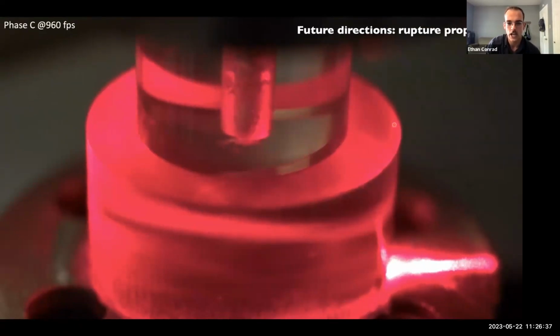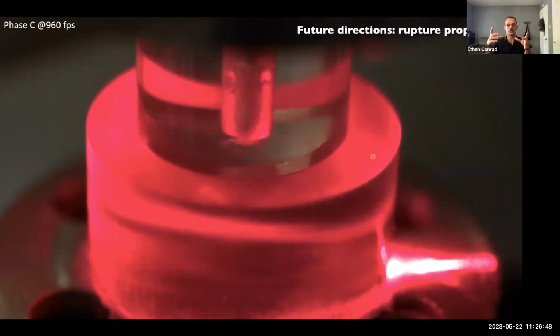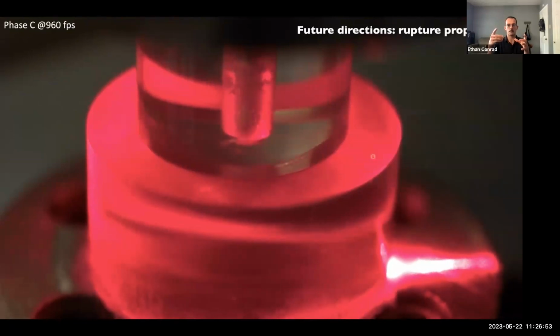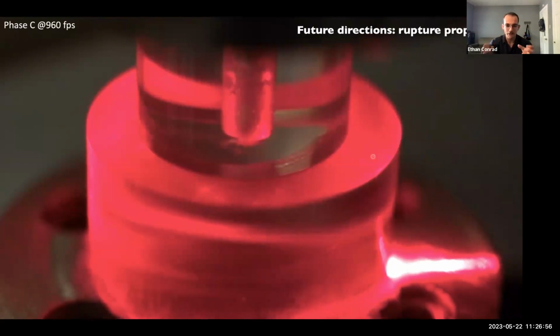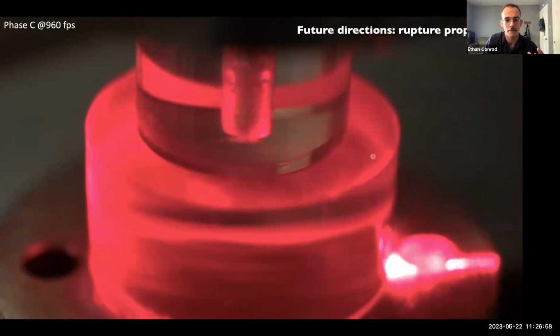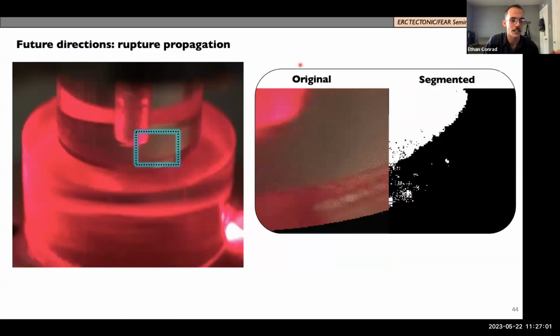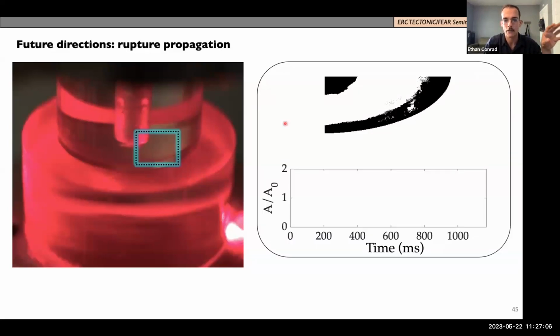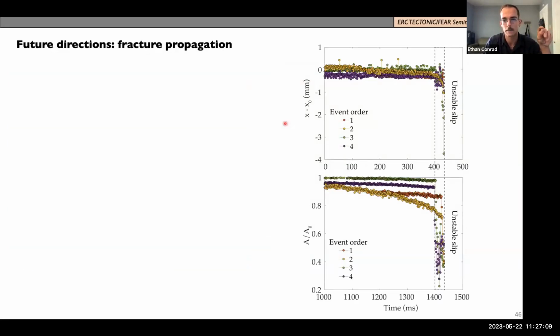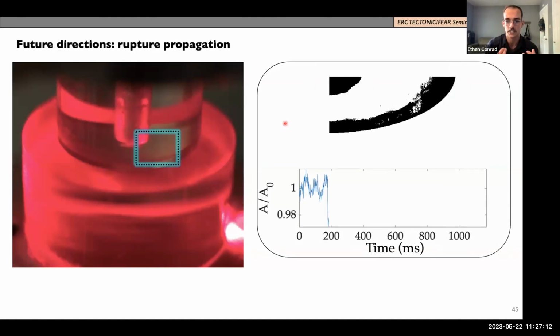Yeah, so the melt patch, checking out this melt patch, we see the patch that's formed, and then we'll start to see it shrink concentrically as you lead towards rupture. So we're watching it. It's moving very slowly, almost imperceptibly, and then it rapidly shrinks, and we see that melt forming with the event. And so what we could do here, for example, is we can segment that image, and then we can actually measure how the area of the interface changes through time leading up to the event.